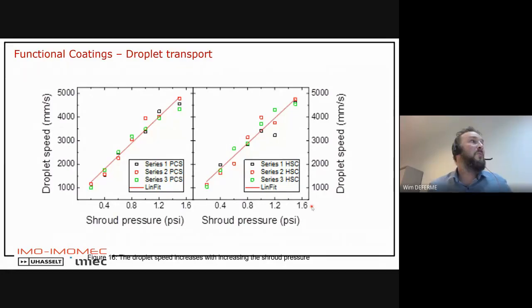And then I said, yeah, it's important to also take the ultrasonic spray coating parameters into account, because you generate your droplets at the nozzle plate, but then of course you have to bring the droplets towards the substrate, and you have a lot of parameters that influence it. I mentioned already the distance between the nozzle and the substrate, the temperature of the substrate. But also, and much more important for droplet transport, is, for example, the shroud pressure. So the pressure applied to the shroud, which is normal, because the higher the pressure, the more energy you give to the droplets or to the surrounding gas that takes these droplets towards the substrate, and you see nice relationships.